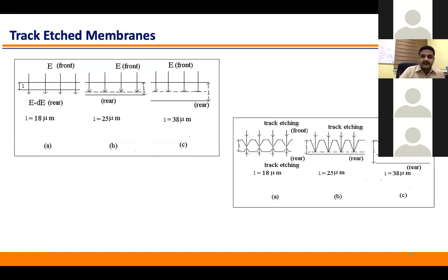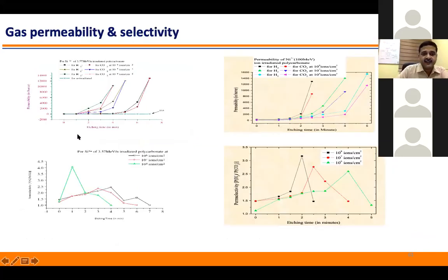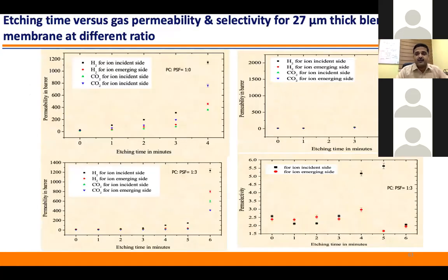And you see the results. So this is the track-etched membrane. What is happening here is, as soon as we increase the time, it means the pore is opening. The pore is too large, so every gas is passing through comfortably, which means permeability is increasing. Gas permeation is fast. But at the same time, if you see the selectivity of these gases, it is being lost. It means around 1 minute of etching time, it is very selective, but after 7 minutes, there is no selectivity.